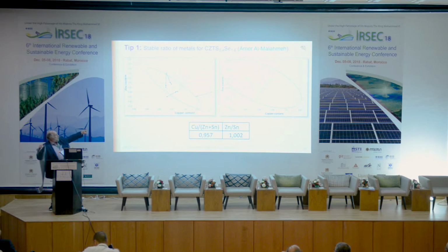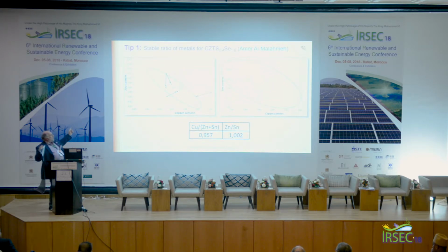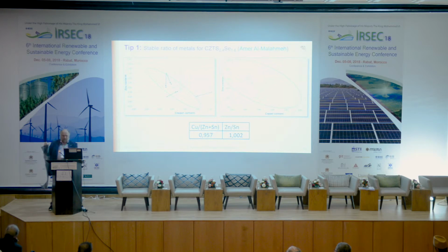except if you start really with the right ratio of these metals. So if you start outside this oval, which is just enlarged on the right side, and it shows the copper content and the zinc content, just taking the content of tin as one, okay? If you start from outside, you will move into this oval, and if you start within the oval, you remain within the oval, so that you come up with one point, actually, where it's completely stable, where input ratio and output ratio is equal.